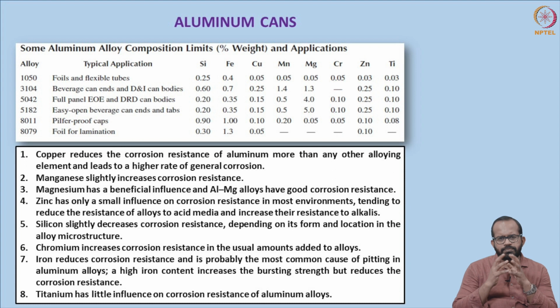Why is copper one of the important components in the case of aluminum cans? Because copper reduces the corrosion resistance of aluminum more than any other alloying element. In the aluminum alloy that is used for canning, copper should be minimum. The aluminum sheet that we are going to use for preparation of canning containers should have copper kept at minimum, because if it is present at higher concentration, it will reduce corrosion resistance. It also increases the rate of general corrosion. Corrosion is one of the problems created by a higher concentration of copper.